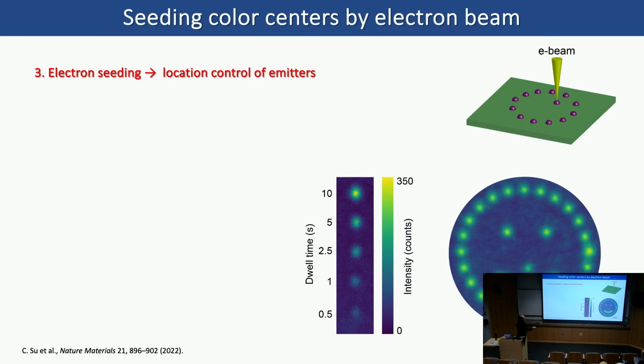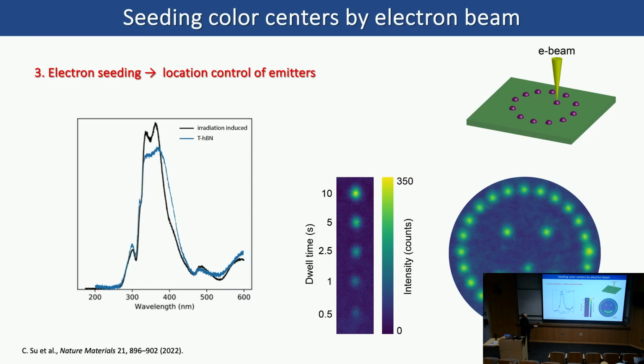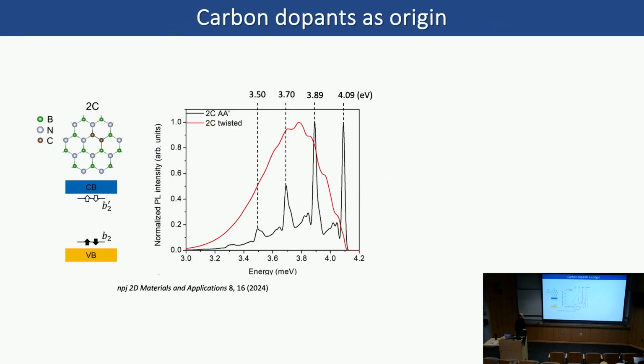Okay, and the third thing we demonstrated is that by using E-beam, this is our ultimate dream, is to use E-beam to deterministically seed defects into some patterns, and we choose a species of these defects. So we did some very simple demonstration and found that with a longer dwell time of this E-beam on a single spot, we could make it brighter and brighter, and we can even draw a smiley face pattern there. And by comparing the emission spectroscopy, we could see that the radiation-induced defects, or these emitters, are actually the same as the twisted hBN. So they're coming from the same source.